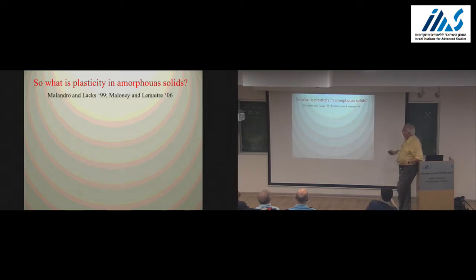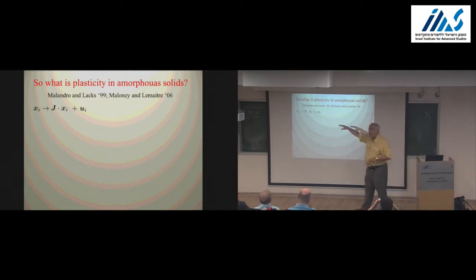Well, what I'm going to describe started with Malandro and Lacks. I personally have learned it from Anaël Lemaître. Then we did a lot of work also with Idan to try to understand what is happening. So basically, at zero temperature, you put a strain on a material. The strain that you choose is determined by a so-called affine transformation. So this, for example, can be: X goes to X plus gamma Y, Y goes to Y, Z goes to Z, so this is pure shear, for example.